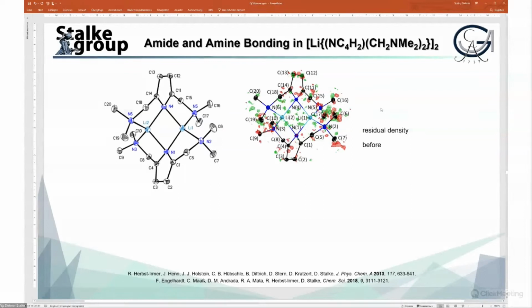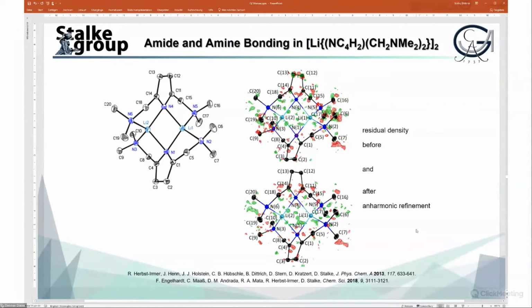Okay, this is what we look at, the residual density when we multipole refine the molecule, and there is clearly the sign of shashlik-like behavior. Depletion in red and accumulation in green, that behaves like a shashlik, like a barbecue. So we have the meat and the paprika, the meat and the paprika, and that is a clear sign for anharmonicity. This was discovered by my dear fellow Regine Herbst-Irmer, and she had a method to cure for that.